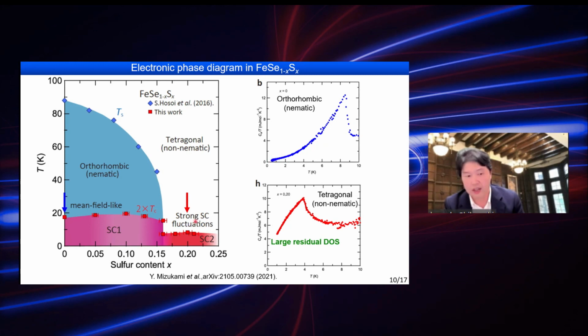And if you go to the tetragonal side, it's completely different from the usual S-wave case. In the S-wave case, you should have a very low residual value, essentially zero, showing exponential dependence at low temperatures. But here we have a very large residual density of states.